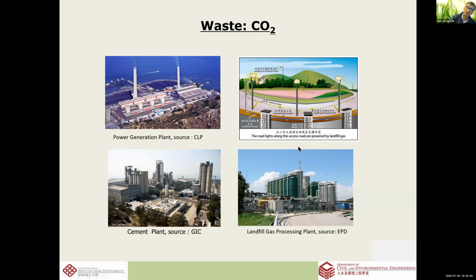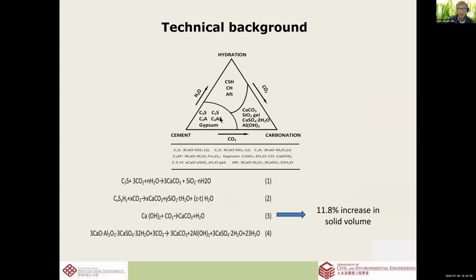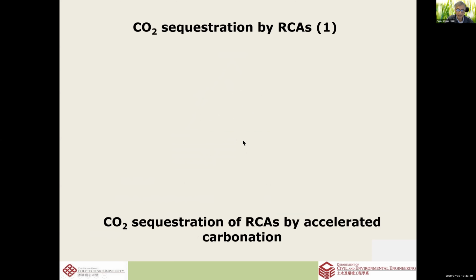So this is a schematic of what we try to do. In the recycled aggregate, cement basically is C3S, C2S and other phases. When it's hydrated, it becomes CSH or CH or AFt. This is in the recycled aggregate. When we carbonate it, we produce calcium carbonate and other things. And with the unhydrated phases in the recycled aggregate, there is still unhydrated C2S, for example, which can still be carbonated into these very stable mineral phases. So that is the principle behind it.